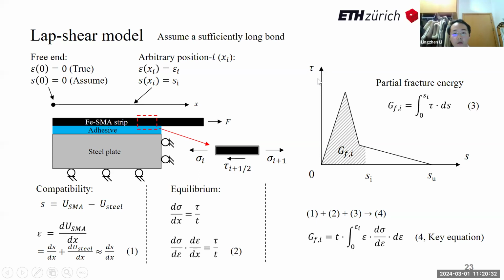Here I need to introduce the bond-slip behavior. The area covered by the bond-slip curve is known as the fracture energy. The fracture energy is the energy required to create new surfaces in the adhesive bond. But when the adhesive is not fully damaged, which means only a part of the energy is dissipated, truncated at an arbitrary slip, I call this fracture energy the partial fracture energy, which is written in this equation. By combining the compatibility equation, equilibrium equation, and the partial fracture energy equation, we have this new equation.